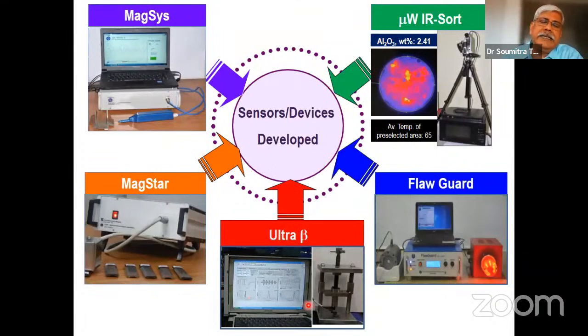The Ultra Beta is a device which is still under development, I would say, but it was very, very promising. It depended on ultrasonics, particularly non-linear ultrasonic, in order to quantify the damage that is created in a component structure. I'm going to talk about some of the background developments in the realm of our R&D that led to the development of this Ultra Beta, which is a portable device which can be used for non-linear ultrasonic examinations of certain type of damages. Non-linear ultrasonic is quite prevalent, but using it for certain type of damages, there is a bit of a twist in it, and that is what we were looking at.